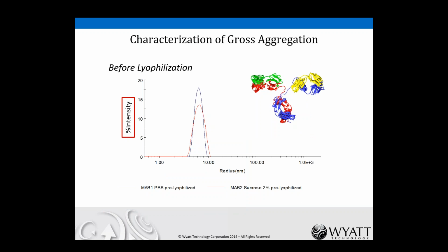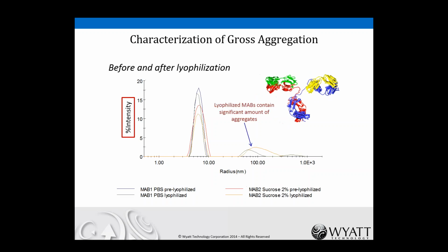So here's an example of characterizing aggregation for a formulation before and after lyophilization. And there are 2 different formulations, one with and one without sucrose. And you can see here before lyophilization, the solution with sucrose has a little bit larger polydispersity, and that may be due to, for instance, small sucrose particles in the solution. It's always nice to have controls, so if you actually had the solution without proteins, you could get an estimate of that as well if those particulates are present. And then go through the lyophilization process and reconstitute and see what happened in terms of aggregation.